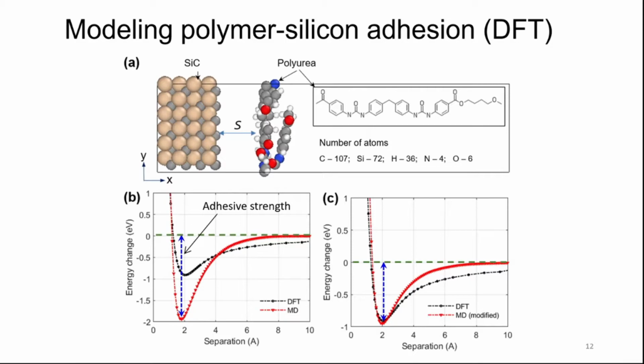In order to properly model the interaction between the ceramic and the polymer, we conducted density functional theory calculations to evaluate the adhesion between the two materials. We computed the energy change as we changed the separation distance between the ceramic and the polymer. And these are the DFT models we use for the calculation, and S is the separation distance.